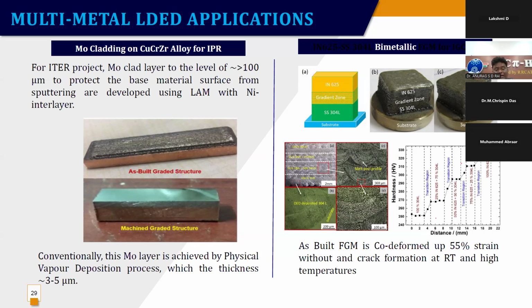So we built components of this, tested the properties, and did the UT of the whole plates. We built a plate of 250 millimeter by 250. Now 1 meter by 1 meter, we are trying to build very soon. This inquiry is going to come to us, and we are going to build this. So that's the way the whole thing can be done. And you see the copper chromium zirconium and molybdenum can be deposited, and once this is done, the thing becomes very different. Something similar we also tried to build in the range of Inconel and SS.